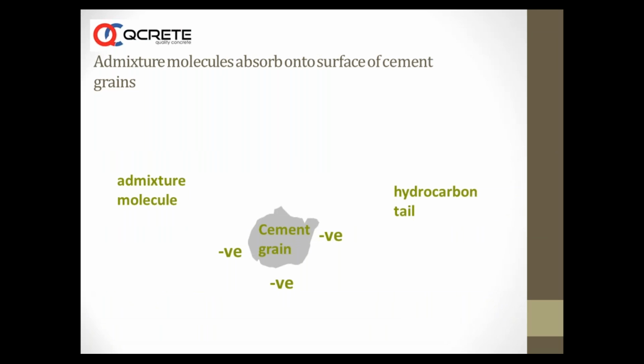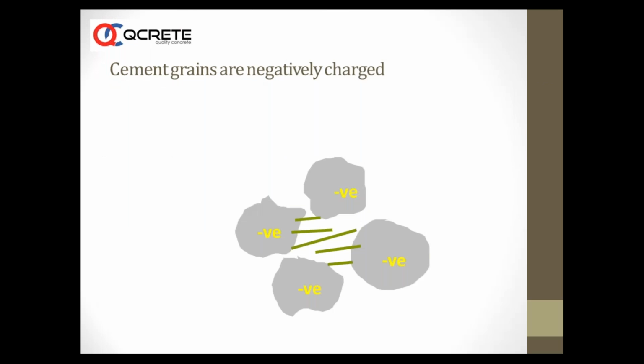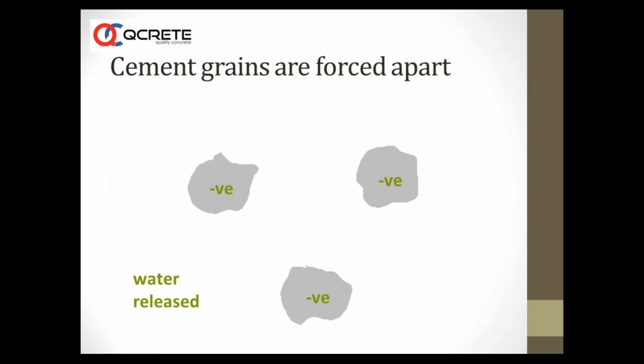When you add a chemical admixture, it induces negative charges, depositing negative charges on the cement particle surface. When several of these charges are deposited on the cement particles, the particles become negatively charged with unidirectional alignment. In the same direction, the negative charges will be aligned, and since the charges are the same, the particles move away from each other, and the water which was erstwhile trapped in the absence of admixture is released.